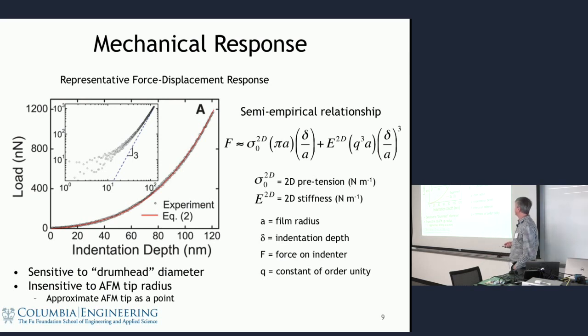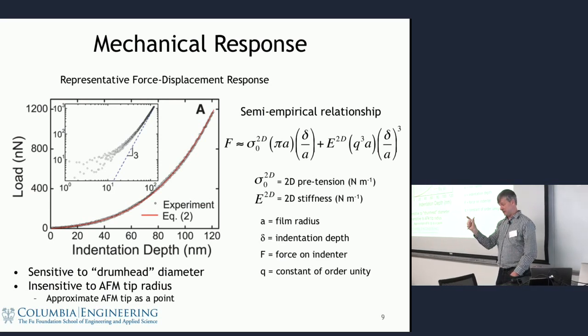And this actually turns out to be relatively easy to understand. I do this when I talk to high school students: you can think about the physics of just a string. If you pull a string, the tension is 2T sine theta. We all did that in the first week of a physics class, free body diagrams and vectors. But as you start to stretch the string, the string gets longer, and the added length goes like theta squared, from cosine theta. The first term is theta squared, which is deflection squared. And therefore the tension is not a constant. We have the built-in tension, whatever we pull the string to, and then the additional tension goes like deflection squared.